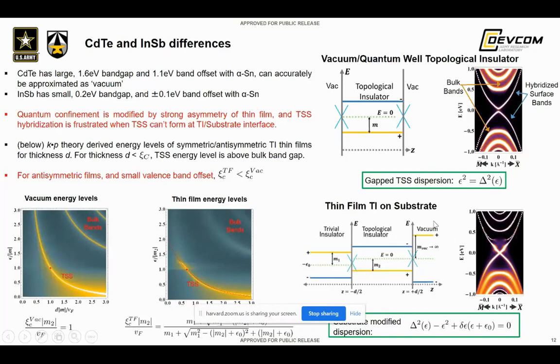Okay, so this slide is somewhat complicated, so I won't go into the details, but the main thing to point out is that due to quantum confinement, CdTe has a large band gap, 1.6 eV, and a 1.1 eV band offset with alpha tin. So you can actually model it as a vacuum quantum well, a confined thick layer. However, in InSb, there's a very small band gap, 0.2 eV, and a very small band offset with alpha tin. Because of that, George can show using some theory that the quantum confinement is modified by strong asymmetry of the confinement of the thin film.